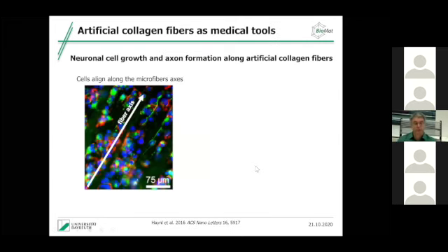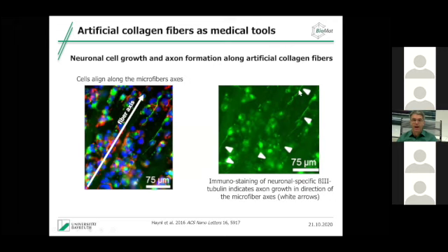But back to the neural regeneration, these collagen fibers that we produce with the microfluidics are also very well suited for neuronal cell growth. And again, the neurites and the axons grow along the fiber axis. And here you see them much better. So we can pre-align the neurons very nicely with these collagen fibers.